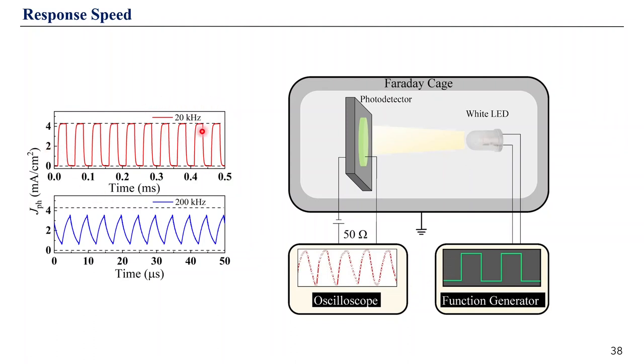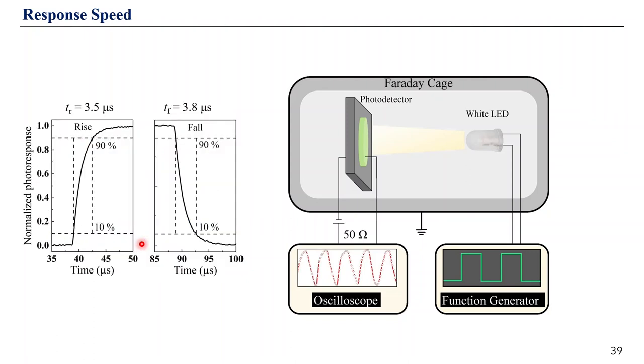So when we deal with low modulation frequency of light intensity, we see quite nice saturation under illumination, then saturation at the dark current. However, if frequency increases, we definitely see some lagging of the photocurrent behind the optical signal. So in order to quantify the response speed of photodiodes, commonly used parameters are rise and fall times. Rise and fall times are defined as the time interval it takes for photocurrent to increase and decrease, respectively, between the levels of photocurrent corresponding to 10 and 90% of the maximum photocurrent. So we got 3.5 microseconds for rise time and 3.8 microseconds for fall time.